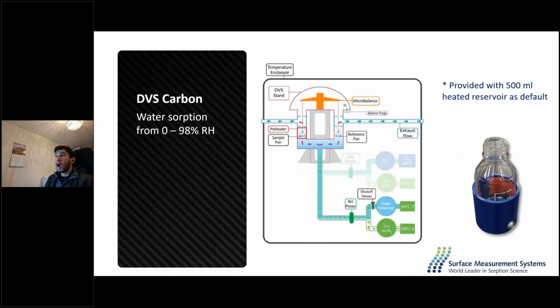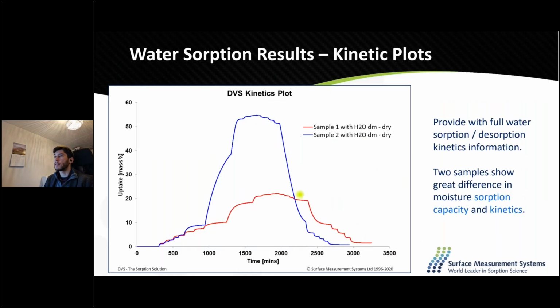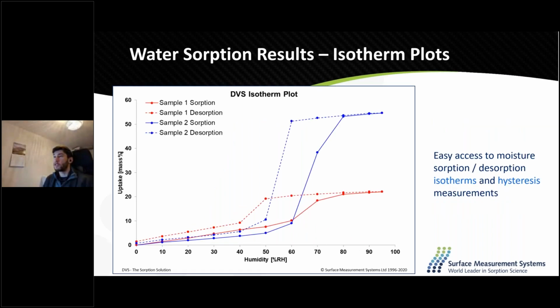So now I'll just give you a couple of examples of data from the DVS carbon. I won't dwell too much on them because I think the more interesting part is the exploration of the molecular sieve, which is coming up later, but I just want to show you a few graphs. So this is, for example, the water isotherms that are recorded. With 2 samples, we can see the kinetics of water sorption and desorption. We can see the mass increasing and decreasing as a function of time. These are processed and can give you the isotherms as a function of humidity, so uptake as a function of humidity. It's pure water, there's no CO2 at this point.